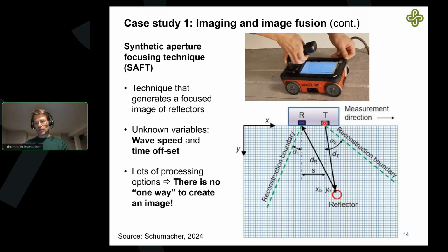So if you send the pulse into the structure, it is reflected. What you do with SAFT is, you divide up this cross section into a grid, and then for each point on the grid, you draw this picture. You basically say, I pretend that this is a reflector. I calculate the distance it takes to travel from the transmitting transducer to the point of interest and then back to the receiving one. I assume a wave velocity that gives me a time.